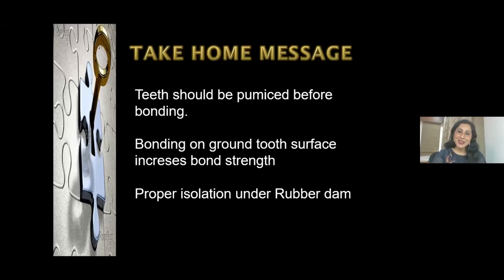Can you change the adhesive? No. Then what can you change? You can change your substrate. You can change the energy of your substrate. So the take-home message is that teeth should always be pumiced before bonding so that the surface energy of the substrate increases. Bonding on ground tooth surface increases bond strength.